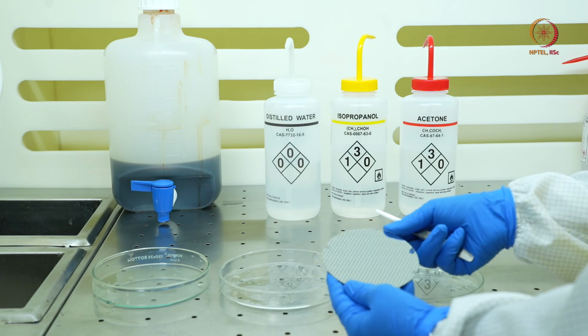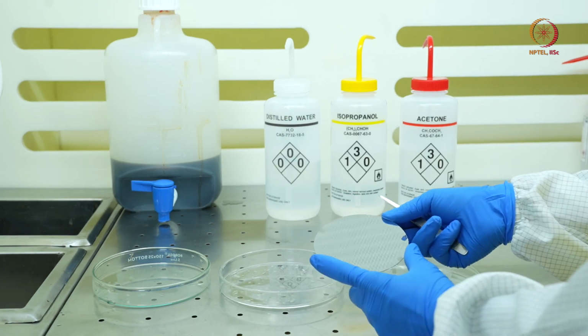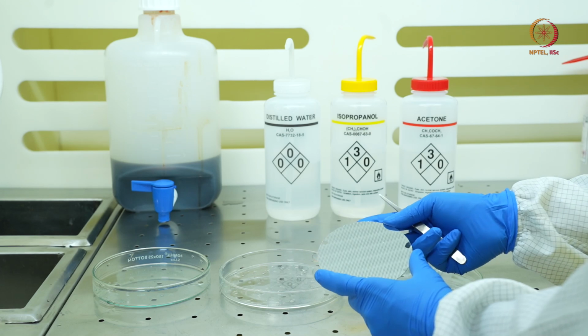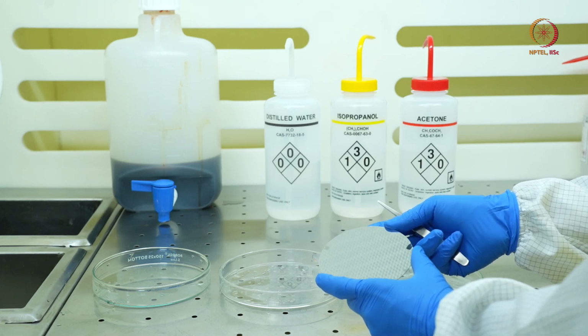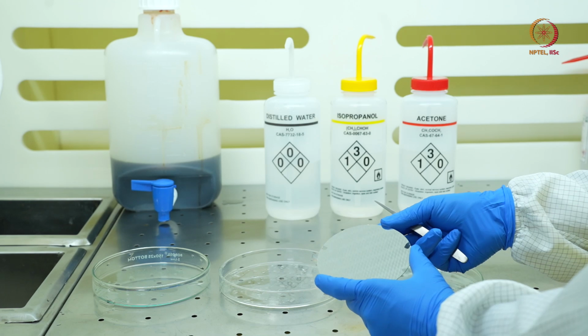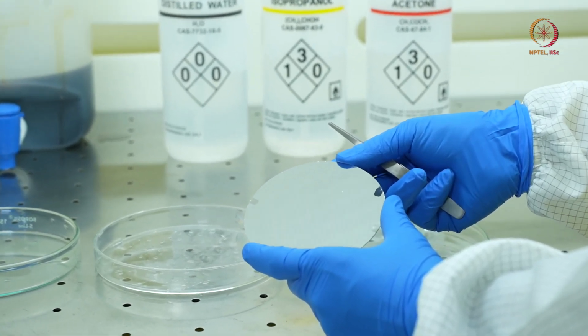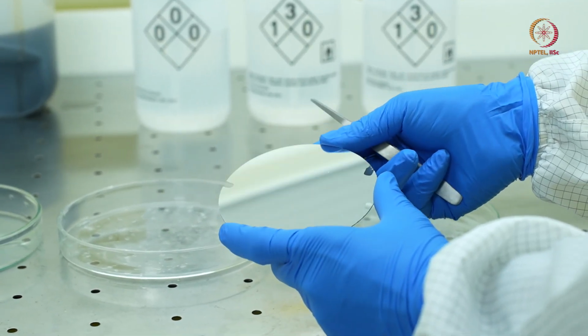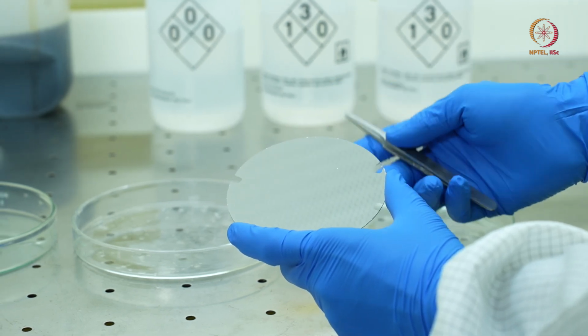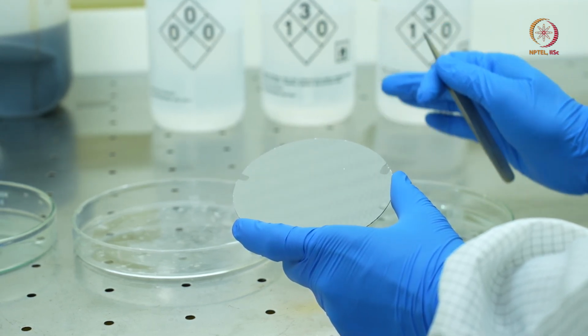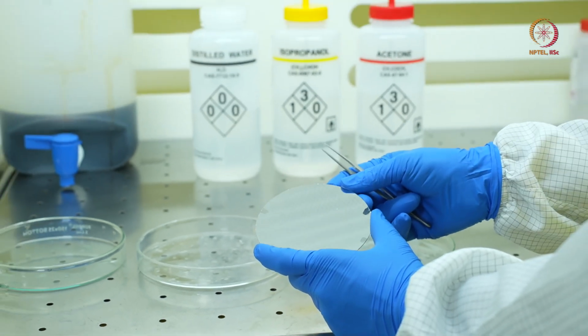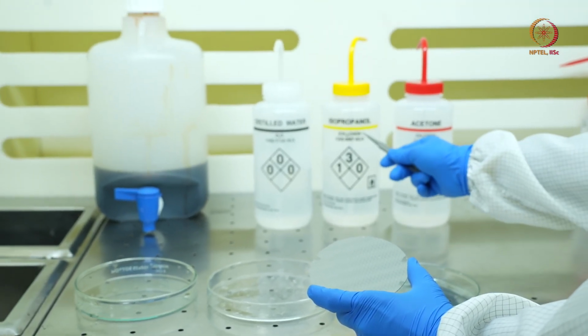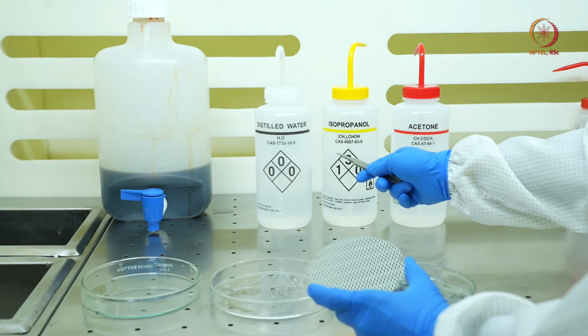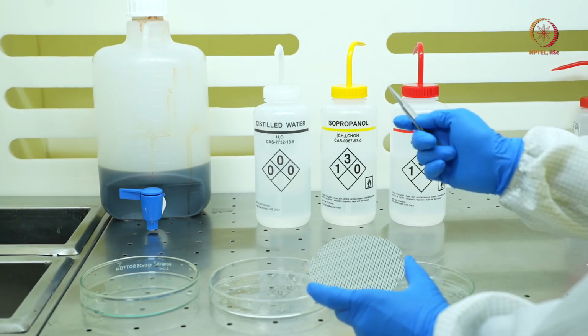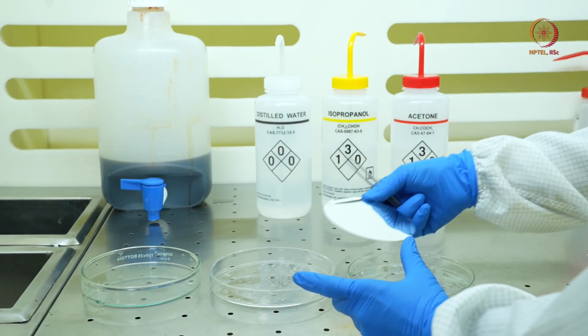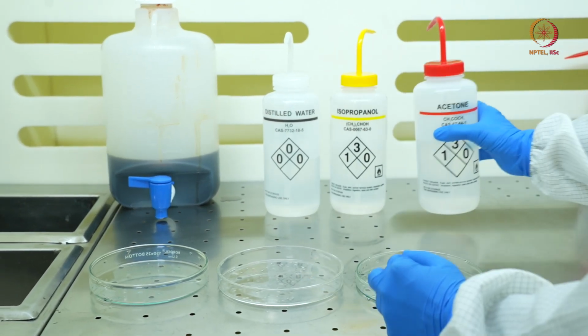Here, as you can see, I have my sample, which is a 4-inch glass wafer, which we have coated with aluminium using thermal deposition. We will do a solvent cleaning on this, and then move to lithography. The first step is to make sure you have all the chemicals that you need. For my solvent cleaning, I'll be using acetone, isopropyl alcohol, and then to wash off the isopropyl alcohol, I'll be using distilled, deionized water. Let me keep my sample aside, and I'll pour the chemicals.